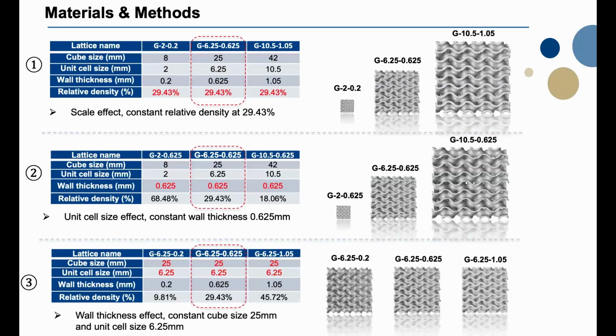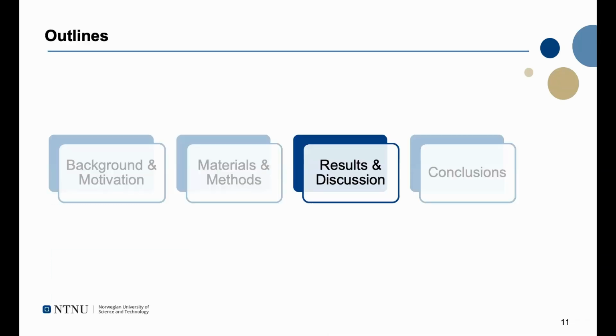And these are all the detailed parameters for all the classifications. As we can see, for the first, the scale effect, all the lattices have the same relative density. For the second, the unit cell size effect, the same wall thickness, and for the third, the same cubic size and unit cell size. Please note that the specimen in the middle can be categorized 3 times, so in total, only 7 geometries were fabricated.